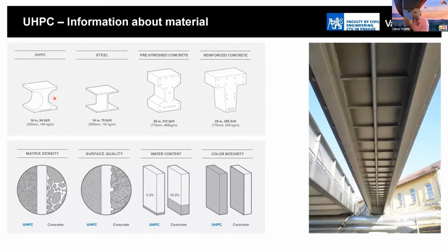UHPC, as I said, the density of the material, or how much material you will spend for 1 meter of the element, is very close from UHPC to the steel. It is 140 kilograms per meter, comparing 110 kilograms per meter for the steel.